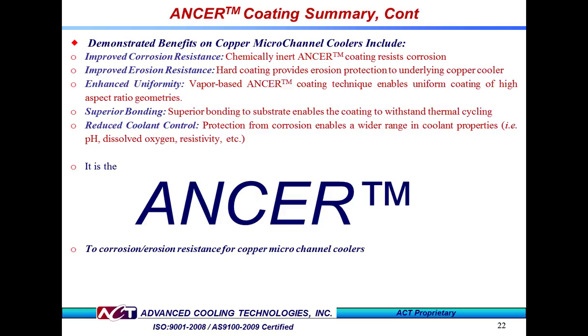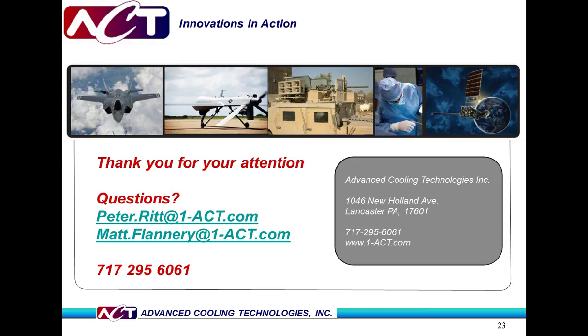that the ANCER coating offers improved corrosion resistance with a chemically inert layer, improved erosion resistance with a hard coating that protects the copper from negative effects of high-velocity DI water systems, a complete conformal pinhole-free coating that can be uniformly applied even on difficult-to-reach internal features, a good, strong bond to the copper and now aluminum surface, a superior coating that can provide this high-level performance, enable relaxed DI water system requirements. It truly is the answer for corrosion, erosion resistance, for copper microchannel coolers, and perhaps many other things as well.